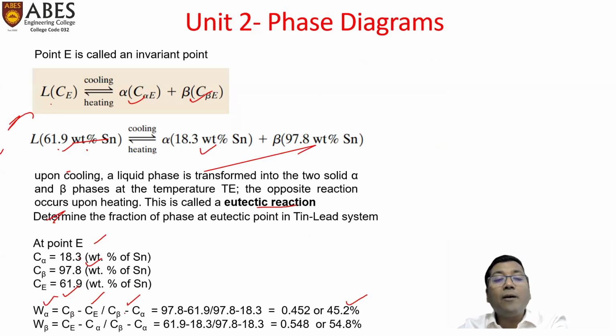Ce minus C alpha upon C beta minus C alpha, and that comes to 54.8%. So the combination of alpha and beta at point E is 45.2% alpha and 54.8% beta. This is how we can calculate from the phase diagram. We can interpret the mass fraction of both the phases present and how the phases are changing as per the composition and temperature variation.